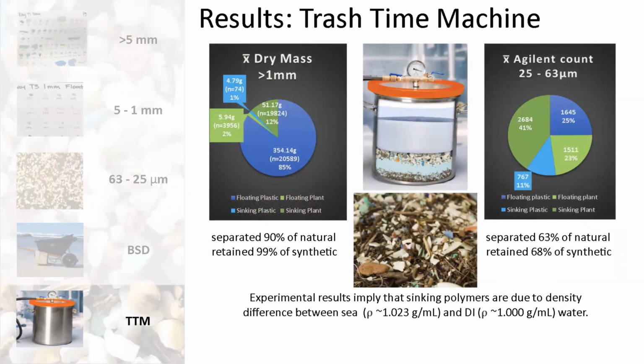So for the trash time machine, everything greater than 1 millimeter in dry mass, over 20,000 particles, this is mean, per quadrant that was removed. Separated, again, 90% of that natural, 99% of synthetics. From Agilent's counts, still good figures. We believe that the sinking of these synthetic polymers is due to the density difference of salt water and the deionized water. Experimental results are showing that that is the reason, but further analysis needs to be done. But the trash time machine works very well.